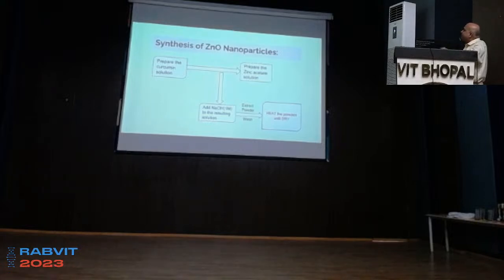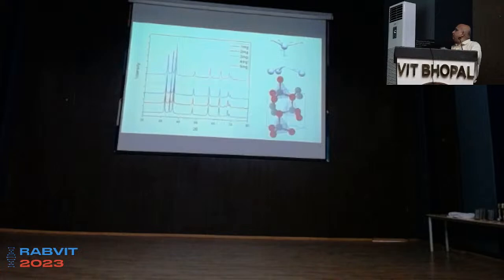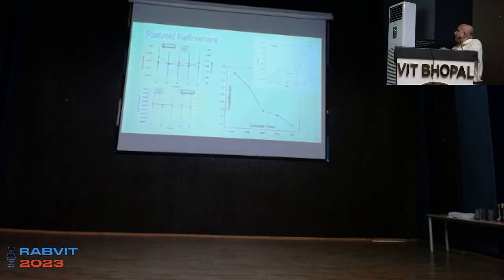And then we extracted the powder, washed it, heated the powders and dried. Now, we found that we got a very nice phase of this material, very phase pure. Although this looks very simple, this took about 6 months to get to the bottom of. Okay? Now, here we found that structurally there is not much change, but the crystallite size has decreased.